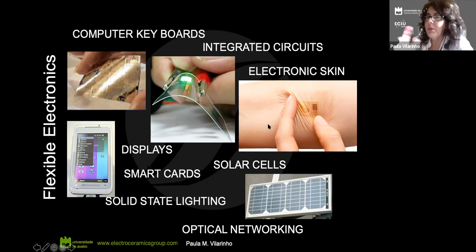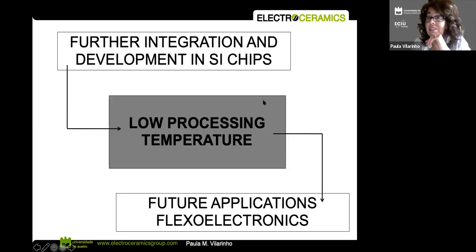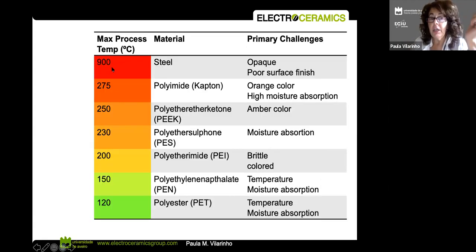So applications for flexible electronics are enormous, as you know. And we have a lot of companies now in Portugal interested in flexible electronics because this can be a commodity sooner or later. But the challenge is, if we want to make them really compatible with oxides, it's low temperature processing, still a very high challenge of processing materials. As you can see here, the maximum temperature that steel can sustain is 900 degrees C without anything happening. However, polyester at 120 degrees C is the maximum temperature you can use. So it's very difficult to make a composite of steel and polyester. This is almost impossible.